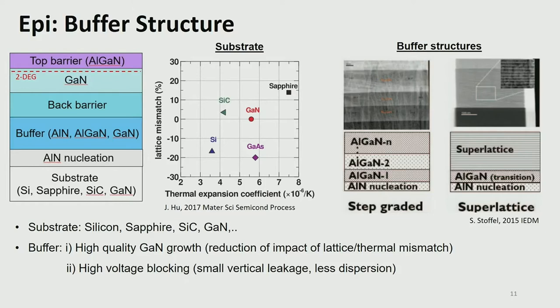But we cannot grow high quality gallium nitride directly on top of the silicon substrate because there is a relatively large lattice constant mismatch. If you see this center figure, there is about 15% lattice constant mismatch between the silicon and the gallium nitride. And also there is a relatively large difference in the thermal expansion coefficient. So to grow the gallium nitride on top of the silicon substrate, we first need to put an aluminum nitride nucleation layer as a foundation, and also we need to put a relatively thick buffer.